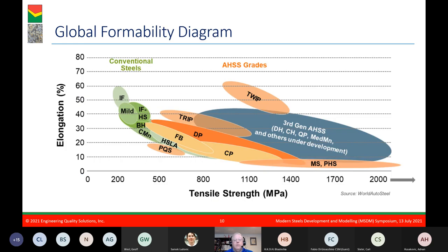The often replicated global formability diagram shows the relative strength, total elongation performance of the many families of steel grades. The latest version now includes press-quenched steels and incorporates the latest production information to generate the size and placement of the bubbles. As more data is gathered, we plan on producing a local formability diagram, which compares strength against a parameter like VDA bending angle or hole expansion ratio. In these diagrams, the relative position of certain grades will change, highlighting, for example, the superior local formability performance of ferrite bainite steels and complex phase steels compared with dual phase steels.